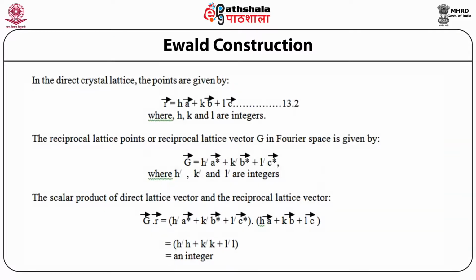In the direct crystal lattice, the points are given by R vector equal to h a vector plus k b vector plus l c vector, given as equation 13.2, where h, k, l are integers. The reciprocal lattice points or reciprocal lattice vector G in Fourier space is given by G vector equal to h prime a star vector plus k prime b star vector plus l prime c star vector, where h prime, k prime and l prime are integers.